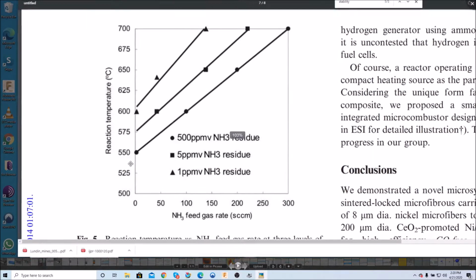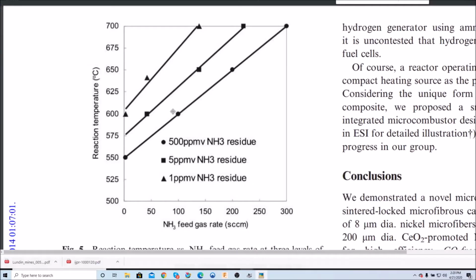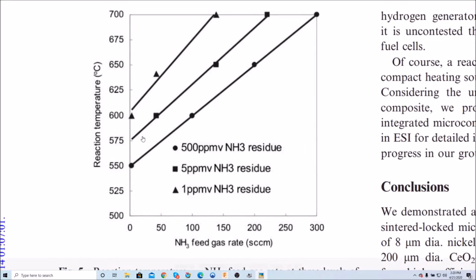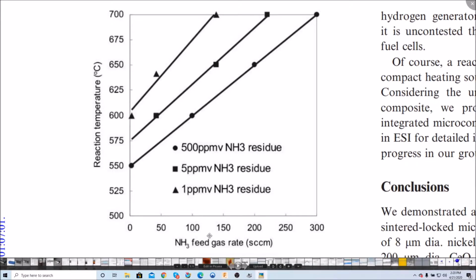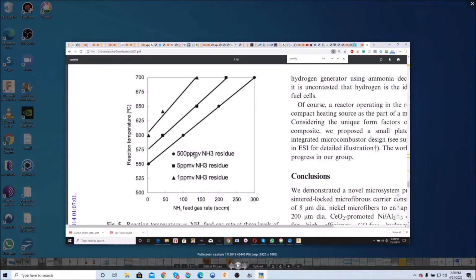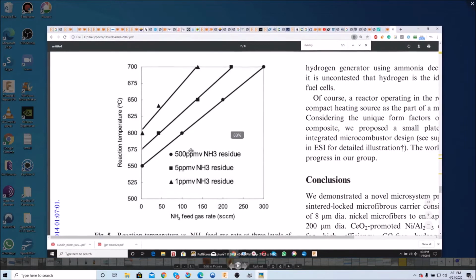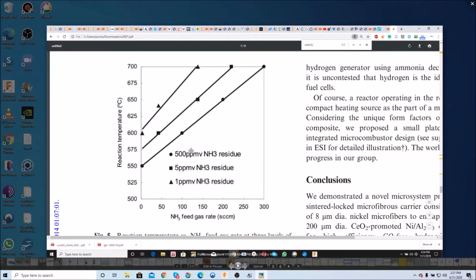So here is the cracker specifications. Okay, so the example of a nickel microfibrous cracker, and here you have the reaction temperature and the residue. So if we assume a feed rate of 150, we go to where it's 650, we have 5 parts per million. And now, of course, 5 parts per million is in excess of what is tolerable by a PEM fuel cell. PEM fuel cells, ideally, you want to be below 100 parts per billion. We can reduce that 5 parts per million to 100 parts per billion using an absorbent, using a carbon-based absorbent.